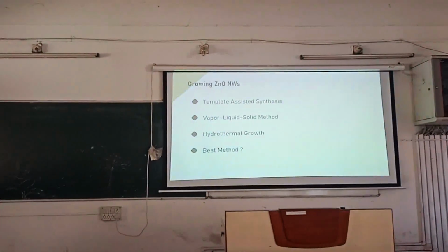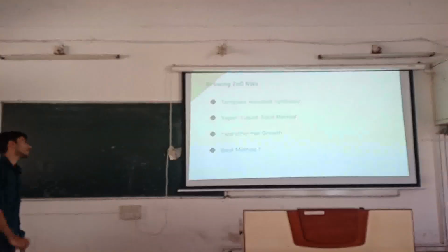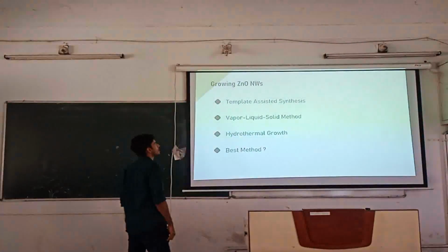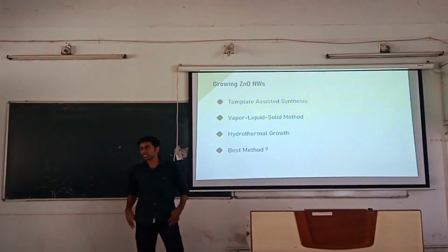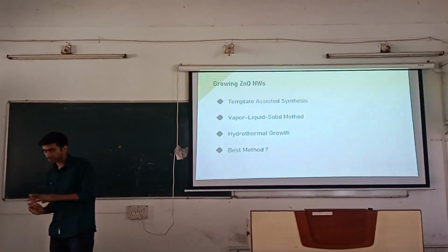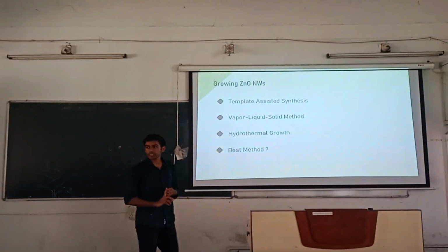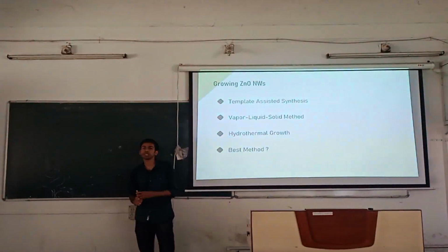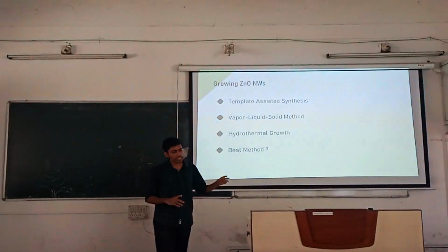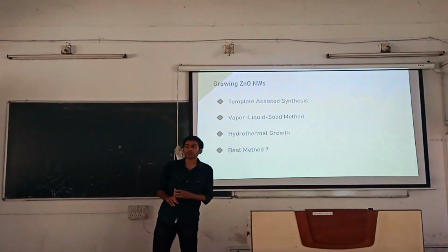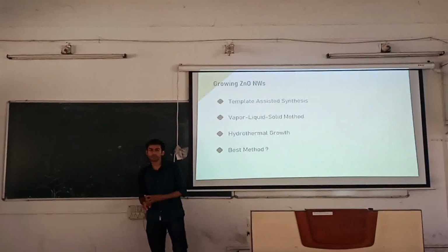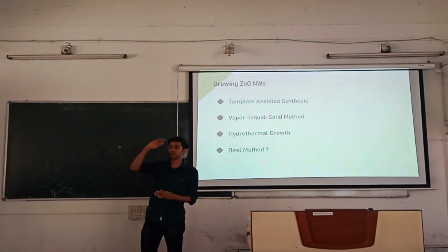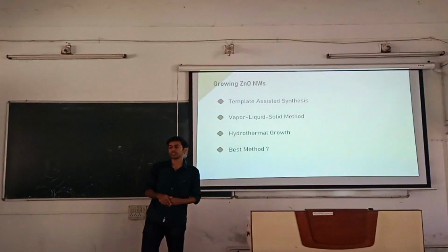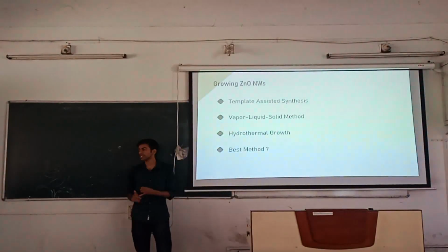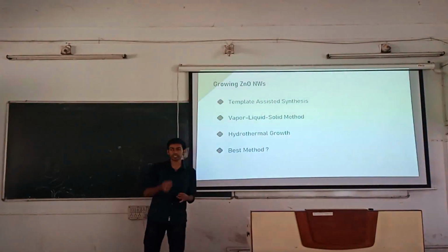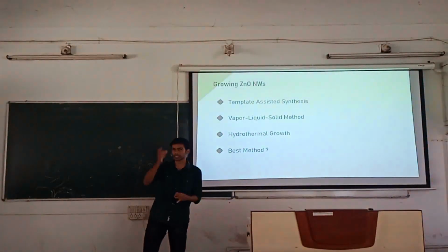Now we'll see how to grow zinc oxide nanowires. There are basically 3 methods, and depending on what we are growing zinc oxide nanowires for, each method has its own benefits and losses. First let me tell you what we require from the nanowires. We saw that piezoelectricity is possible only along the C axis. So all our nanowires should be oriented along the C axis. Everything should be hexagonal and standing straight.